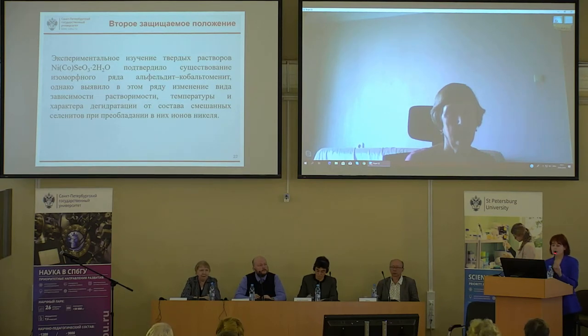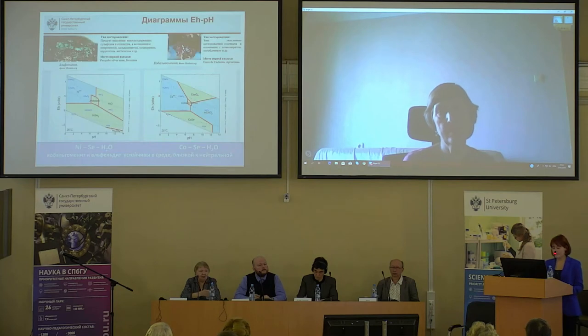Thus, the work carried out has allowed us to formulate the following provision. An experimental study of solid solutions confirmed the existence of an isomorphic series of ahlfeldite-cobaltomenite, but revealed in this series a change in the dependence of solubility, temperature, and nature of dehydration on the composition of mixed selenites, with nickel ions predominating in them.